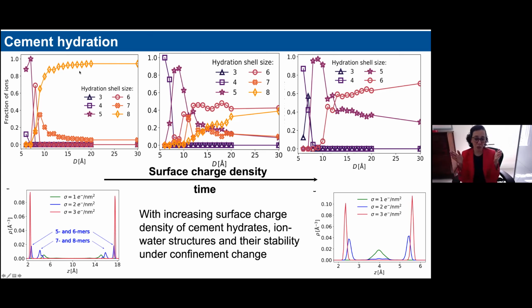And then when you start to increase the confinement, you can stabilize the system and get cohesion by changing the hydration, the water-ion structure, right? But then you need to break these hydration shells, and this effect can produce intermediate-range repulsions that are in fact seen in AFM measurements of surface forces between CSH nanoparticles during cement hydration.